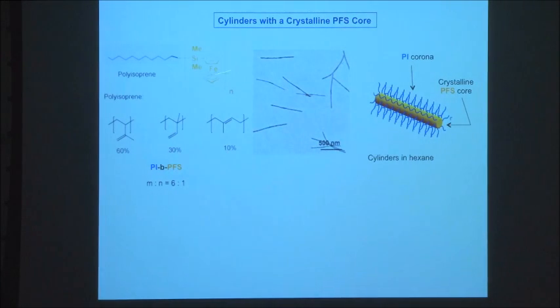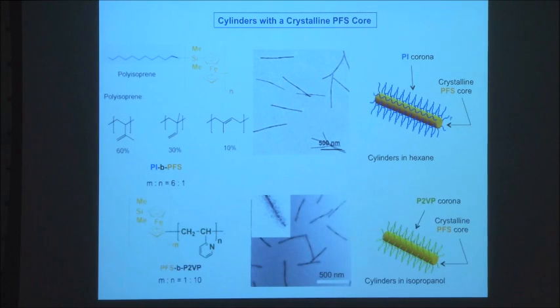And you can do the same thing with these other materials. So if you take dimethyl PFS polyisoprene, dissolve in THF, add hexanes slowly, you generate, again, nice cylinders. Here with a polyisoprene corona in blue, again, you can show you have a crystalline dimethyl PFS core here. And you can do it with the hydrophilic analog, where you have a poly-2-vinyl pyridine shell here. Here you do the self-assembly in isopropanol, which is a good solvent for poly-2-vinyl pyridine. It's poor for the dimethyl PFS. But again, you get cylinders, crystalline dimethyl PFS core on a poly-2-vinyl pyridine corona, which stabilizes the structure and gives you colloidal stability in isopropanol here. An interesting thing to think about is how the PFS chains actually crystallize in the core here, and I'll come back to that issue a little bit later on.